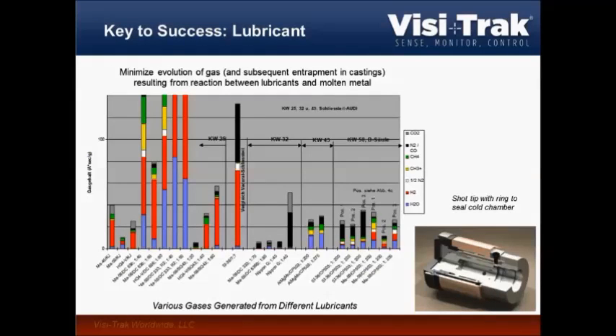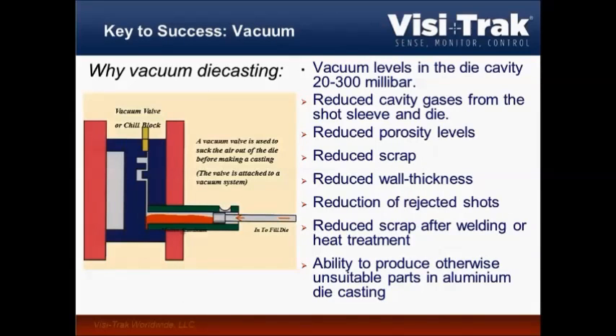So when we then talk about lubricants, and we mentioned that before, they are a big source of problems in structural die castings. So there are a lot of things to watch out for, but the main thing is never have too much of it, and you need to apply it properly. Both the plunger lubricant and the die lubricant, of course. There isn't just one lubricant that's the best and the only one that works. You will find different technologies and strategies to do that, but it's a very important aspect that needs to be taken into account. Otherwise, it easily destroys your vacuum.